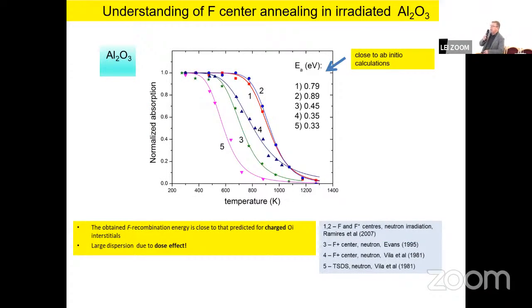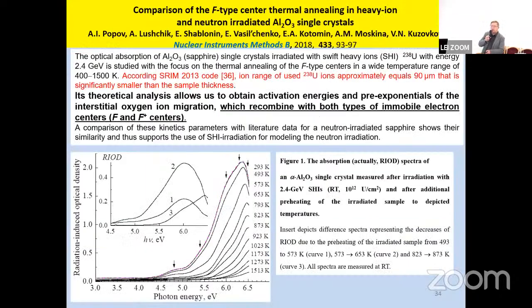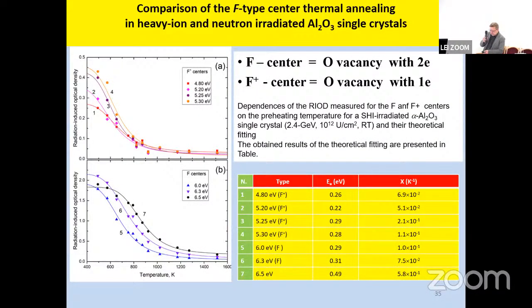So we continue this business for other materials. Firstly, when I analyze alumina, you can see this is literature data from 4 different papers. There is a huge difference between the shape of the annealing curve. We performed our experiment just to know the radiation condition for defect annealing in alumina. This was performed with a sample which was irradiated in Darmstadt at GSI by uranium ions, as I remember. And after we performed very careful thermal annealing. So the sample was heated, cooled down, measured, in several stages.